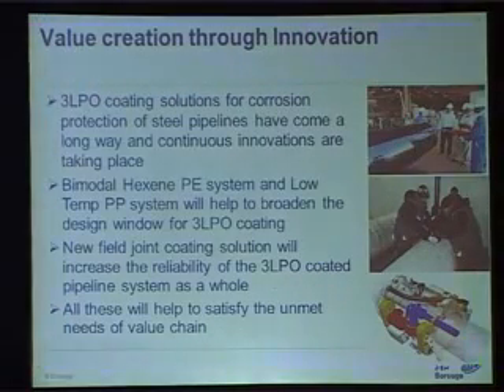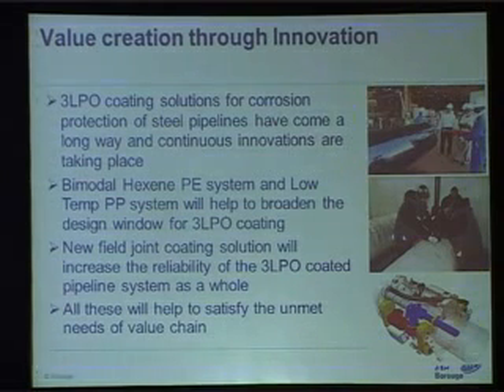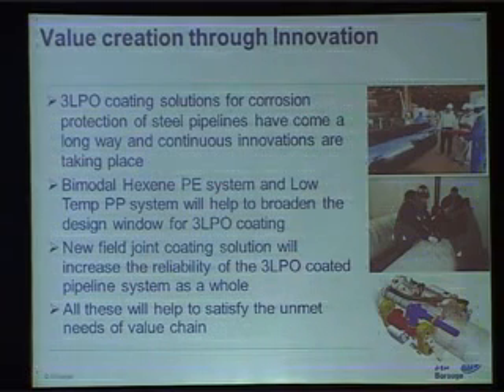Coming to the conclusion, 3-layer polyolefin coating solutions for corrosion protection of steel pipelines have come a long way, and continuous innovations are taking place. We have shown you bimodal hexene PE system and low temperature PP system will help to broaden the design window for 3-layer polyolefin coating. New field joint coating solution will increase the reliability of the 3LPO coated pipeline as a whole. All this will help to satisfy the unmet needs of the value chain.